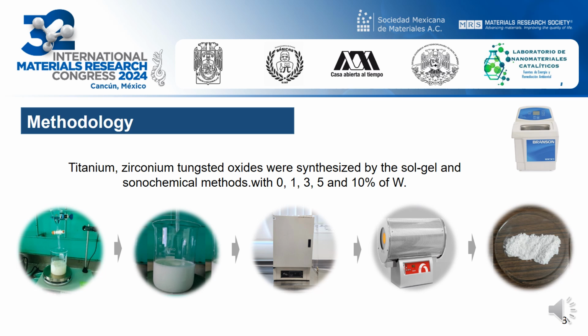Finally, the sonochemical method followed the same synthesis procedure, adding exposure to cavitation in a Branson 8890 ultrasonic bath with a frequency of 40 kHz. The catalysts were characterized by X-ray diffraction, nitrogen physisorption, carbon dioxide and ammonia temperature-programmed desorption, and scanning electron microscopy.